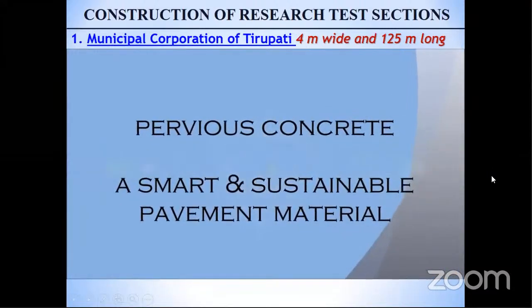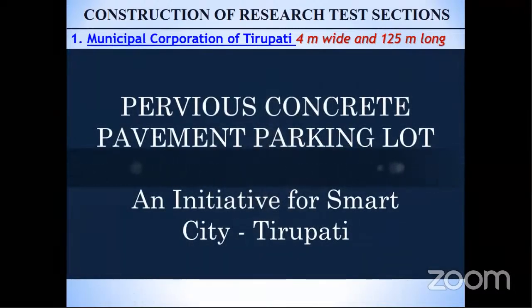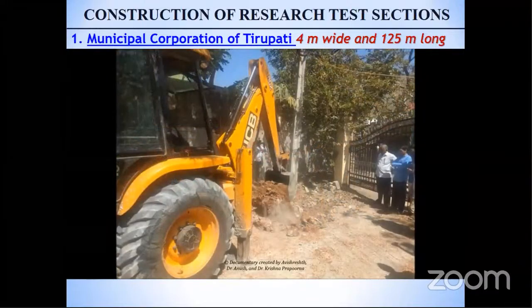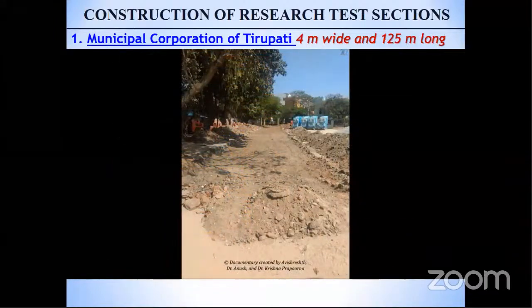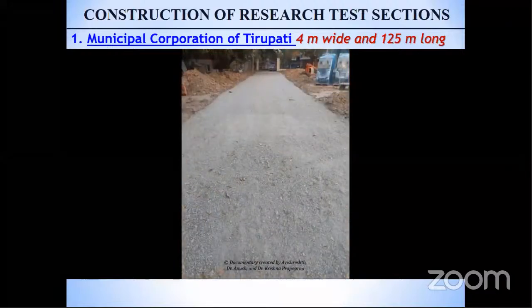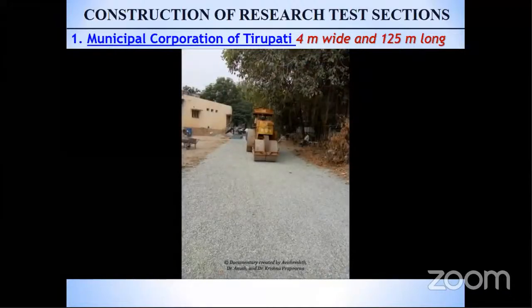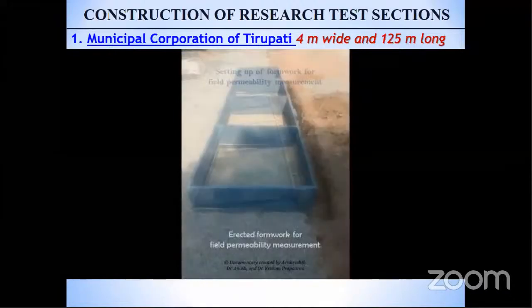Now, in order to give you more insights on how these research test sections were constructed, I would like to show you a small video. Now, as you see, this was an initiative for Smart City Tirupati. First of all, the string lines were drawn and the subgrade was excavated and prepared by passing about 10 to 12 passes of a static steel wheel roller. Then granular sub-base material was laid and it was compacted again by about 6 to 8 passes of a static steel wheel roller. A formwork was erected towards one of the sides.